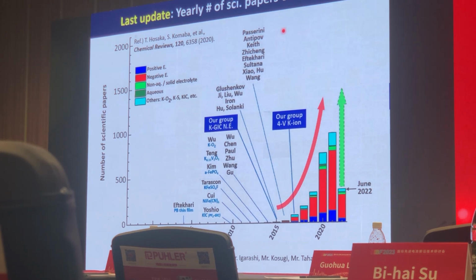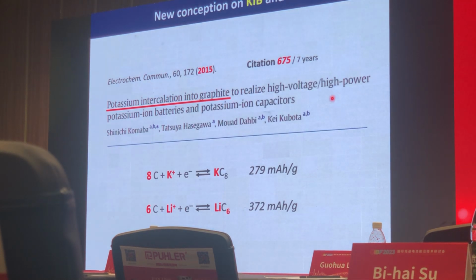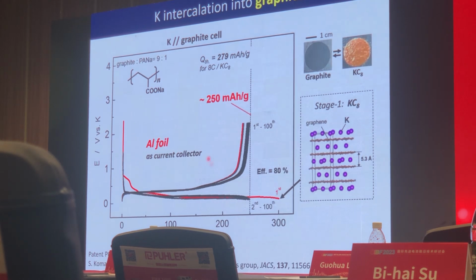Because of our success with the potassium ion cell, for forward potassium GIC and full cell based on iron manganese positive electrode, the number of publications drastically increased. Our first report on potassium intercalation into graphite was published 8 years ago, and KC8 is the highest concentration of potassium in graphite, which is lower than lithium, but with comparable reversible capacity to the lithium case. And we also have to select a good binder like polyacrylate and a good electrolyte solution.